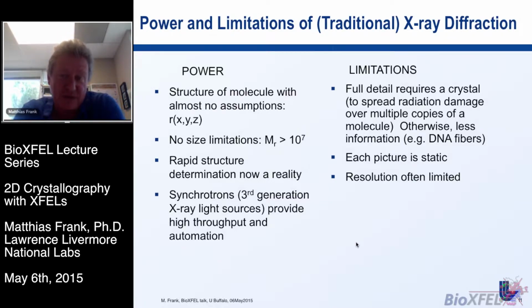The limitation, of course, is that X-rays are damaging. Radiation damage is an issue, which is the reason why you need a crystal to do the measurement, why you can't do it on single molecules. So you're basically spreading the radiation damage out over a large number of copies of identical molecules. And another limitation is that if you do that in the crystal and the crystal is cooled, it's mostly static. So you don't see any molecular dynamics. Although that's not entirely true, there have been time-resolved studies in crystallography that were quite successful.